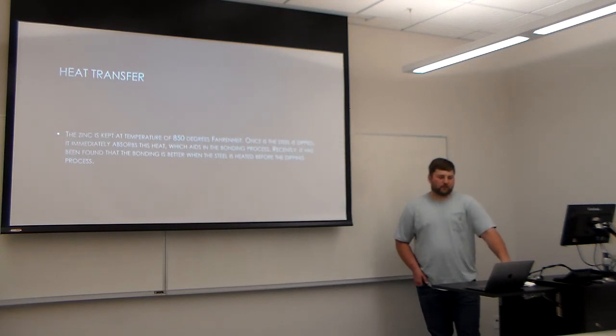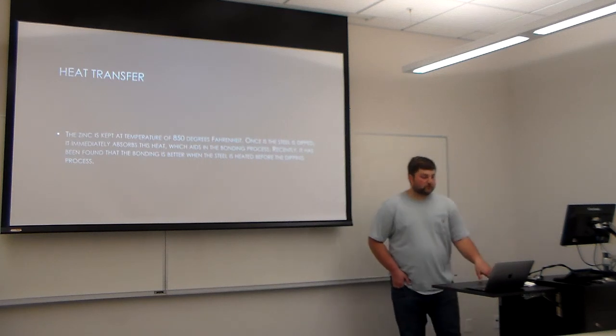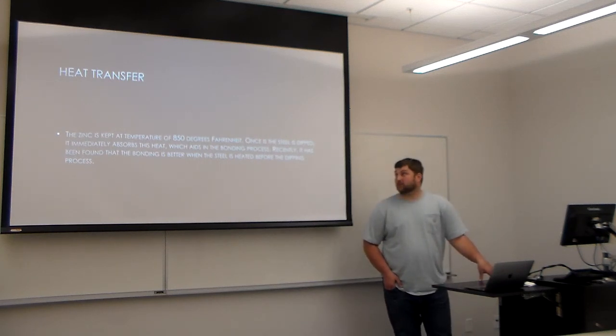But something that we've found recently is that the hotter the steel is when it goes in, the better the zinc will actually stick. So it does you much better to heat your steel up. That way your heat transfer rate can be lower. Even though your heat transfer is going to be slower, it actually speeds up the process at which you can get your coating on there.